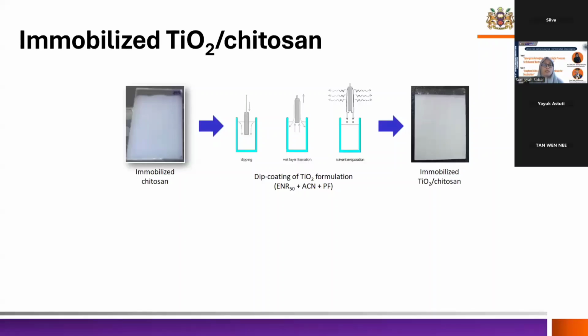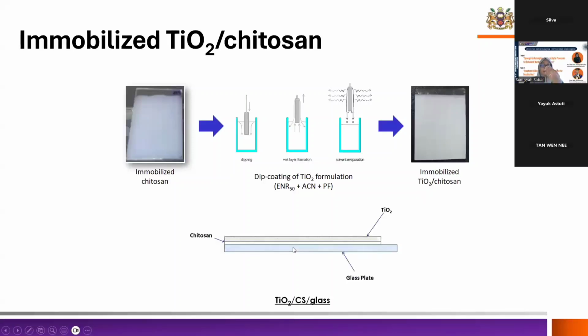So what we did was that we tried to immobilize the chitosan onto a glass plate, and then we prepared a TiO2 formulation, which is made from ENR50, which is epoxy natural rubber, acetonitrile, and also phenol formaldehyde. So once the TiO2 formulation was prepared, we dip coat it onto the immobilized chitosan, and you will get this immobilized TiO2 chitosan. If you look at the cross section of this material, we have the glass plate as the support, the chitosan as the second layer, and TiO2 at the top. This is what we call a layer by layer titanium dioxide chitosan glass.